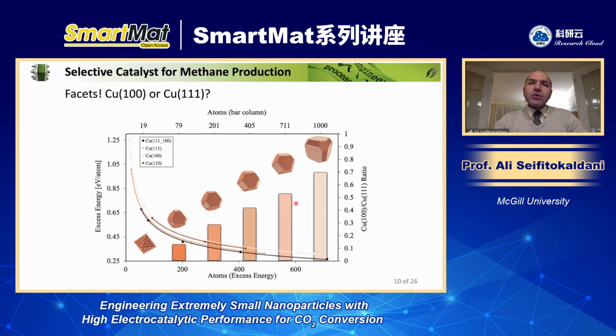So people show that if you use copper with the 100 crystalline facet, you most likely get a lot of ethylene. And vice versa, if you have single crystal copper with the 111 facet, you most likely get methane, not a significant amount of ethylene. And then there are also other works showing a relationship between product selectivity and particle size, for which they demonstrate, for example, that by changing the particle size, you may also change the selectivity. But in literature, people work with very large particles, such as 1 micron or even larger, down to very small particles, such as 25 nanometer particle size for copper.